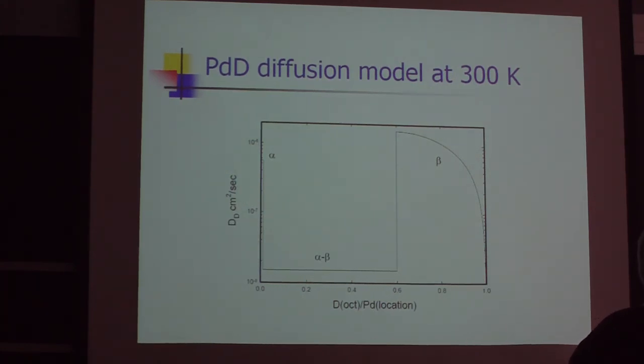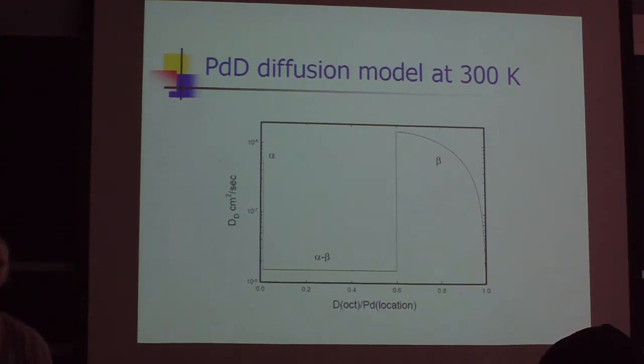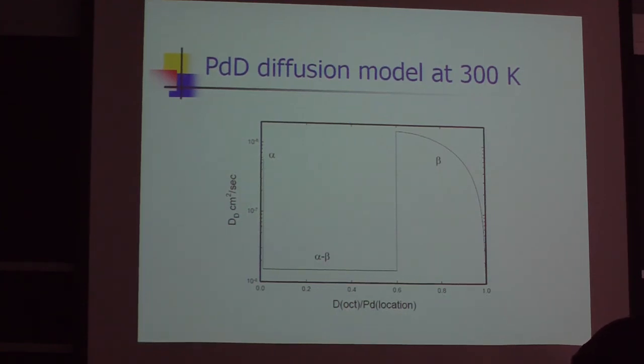Yeah, it seems like that's based on microstructure and morphology. But it should be possible to get a single crystal of palladium to eliminate grain boundaries. Then imagine a very long, slow experiment measuring diffusion carefully. One of these days, somebody needs to do those experiments cleanly with thin palladium foil at different temperatures and generate these curves. I don't like working with a bolted-together curve; it doesn't give precision information.